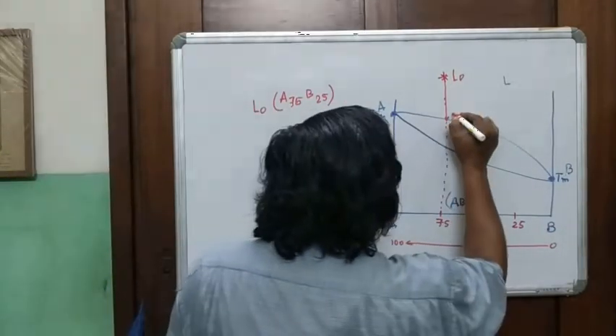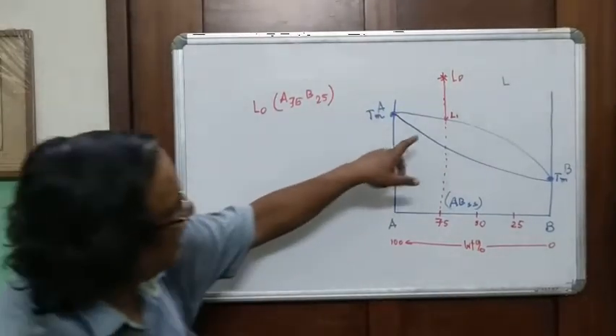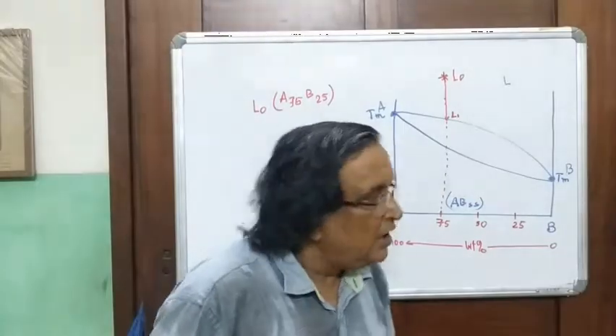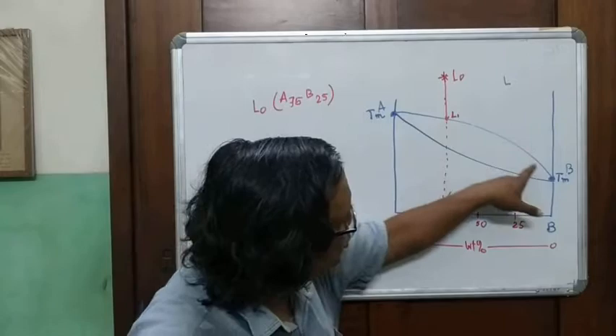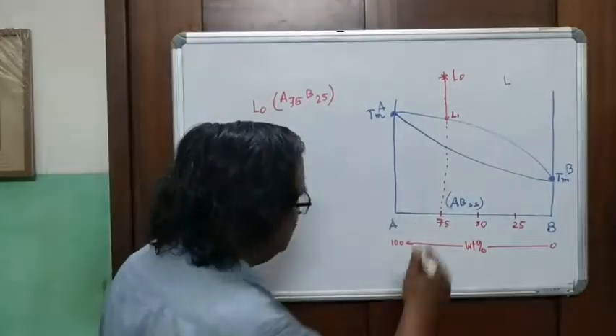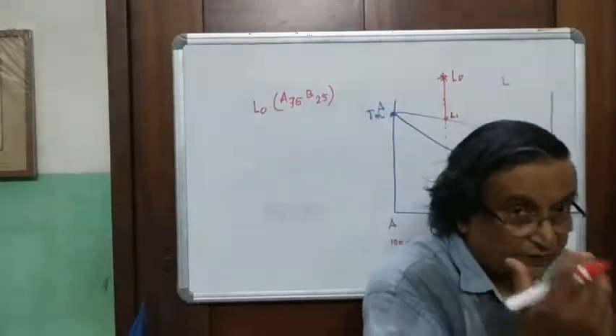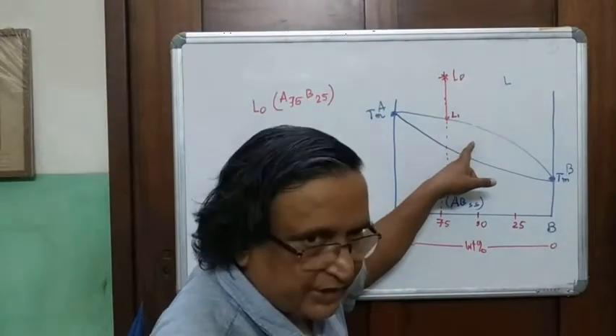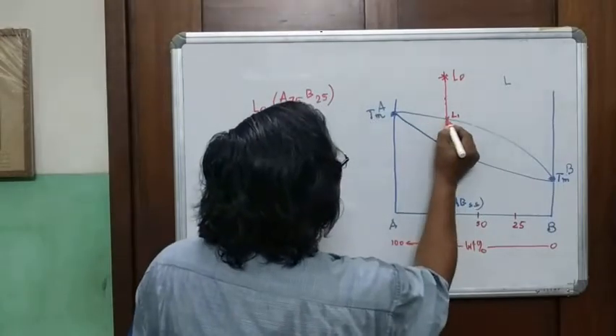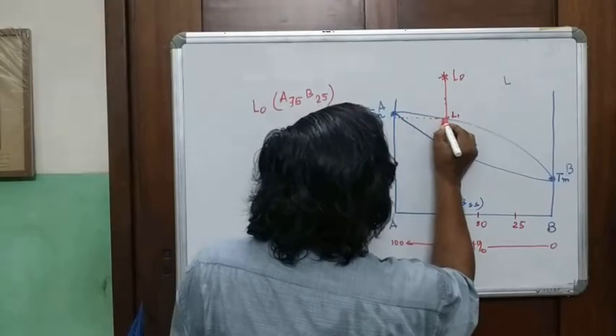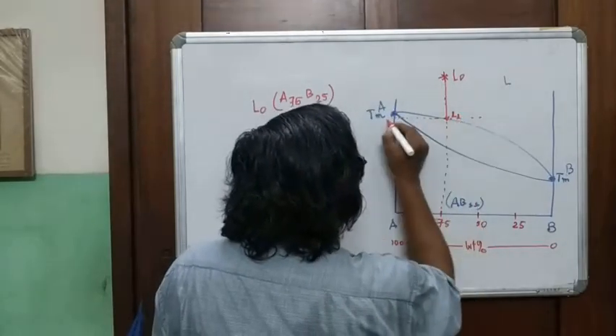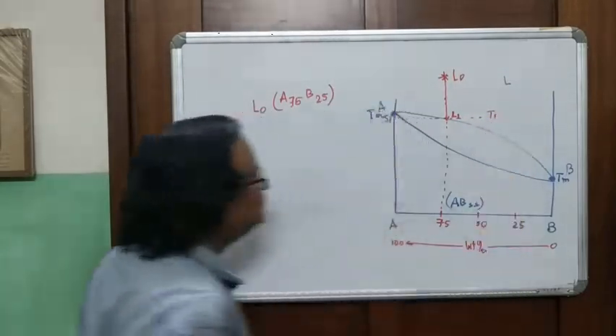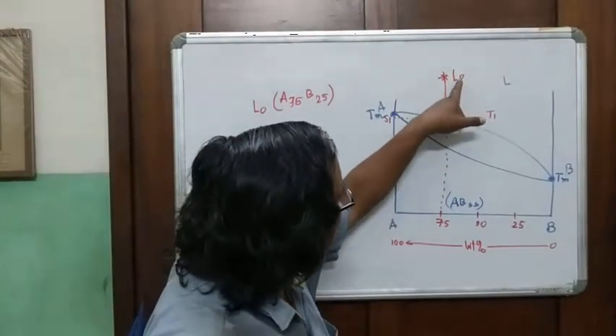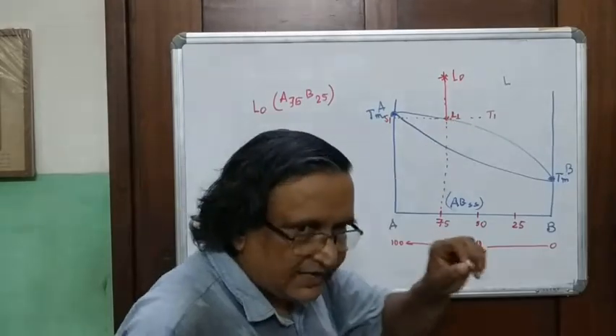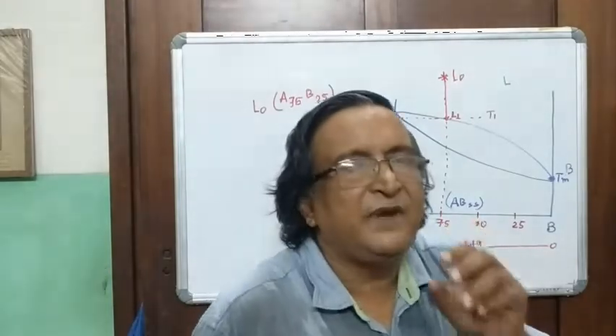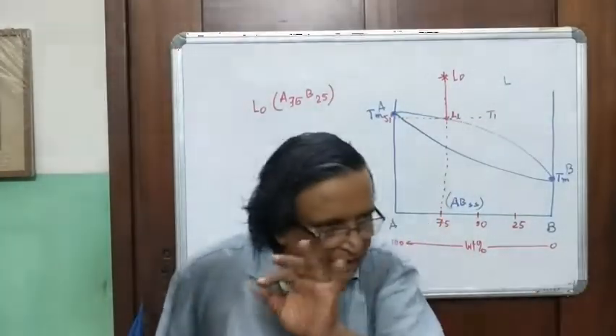So this point is, let's say, L1, and this point is what is called the liquidus. At this point, this field is AB solid solution plus liquid. So what happens the moment you're on the liquidus, you should be precipitating, because the liquid is in equilibrium with AB solid solution. So if this is the liquid, then this liquid intersects the liquidus at this particular temperature. If this is L1, then this is S1, and the temperature is T1. So at this temperature T1, when the liquid composition reaches T1, that means it lies on the liquidus. Immediately, the requirement has to be fulfilled that the liquid has to be in equilibrium with the solid.